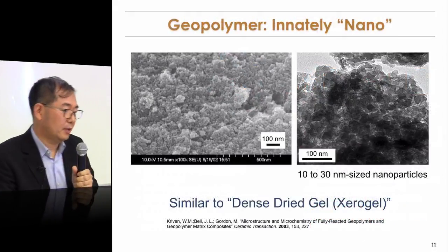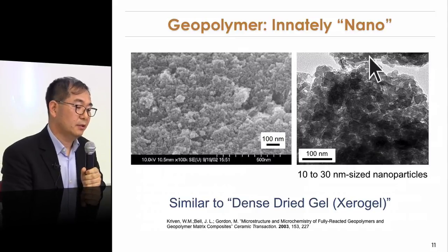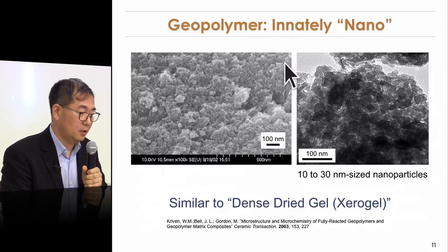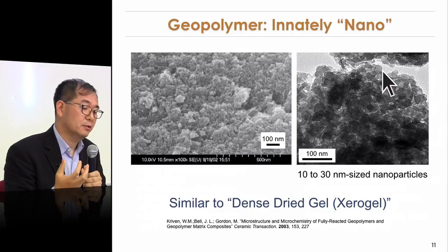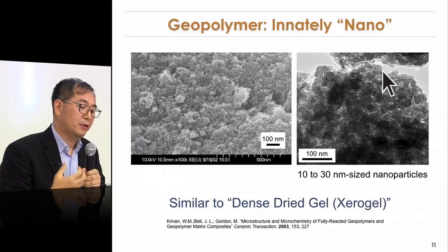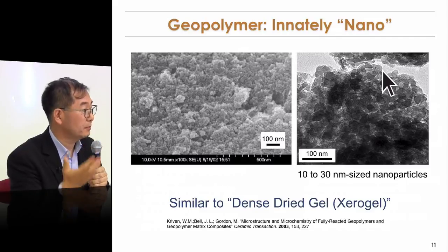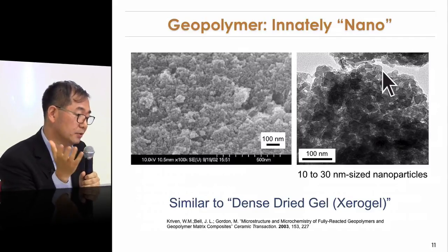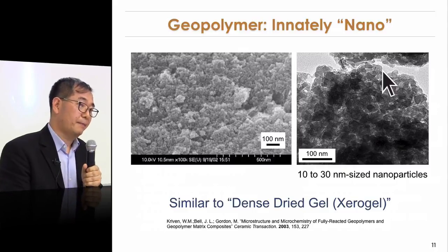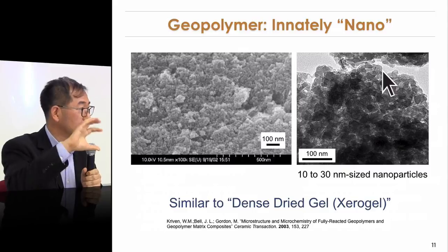So how do we do it for nano aggregates? Going back to this, the TEM image as inspiration. We just want to open up this structure and break up this network structure. Then what we do is just add more sodium hydroxide or potassium hydroxide, so that generates more hydroxide-terminated surface. And also, we add more water, so that provides more void, basically.